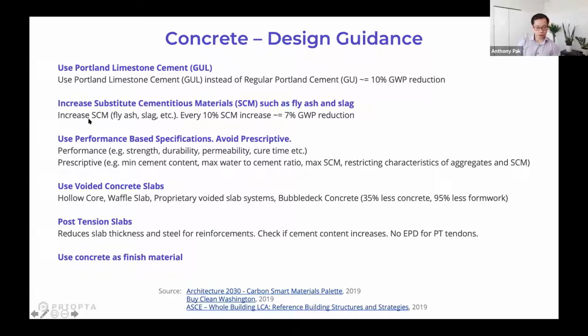And then from there, you can also increase supplementary cementitious materials, things like fly ash or slag. Again, those generally correlate with reducing the cement content in the concrete mix. These are just based on my own estimates, but roughly, from some of the numbers I've seen, every 10% increase in the SCM content leads to about a 7% reduction in embodied carbon of the concrete mix. Again, these are high level numbers, but the key point is that you want to optimize it by building element. As you have higher SCM content, it can affect your curing times, and that's just one of the considerations.